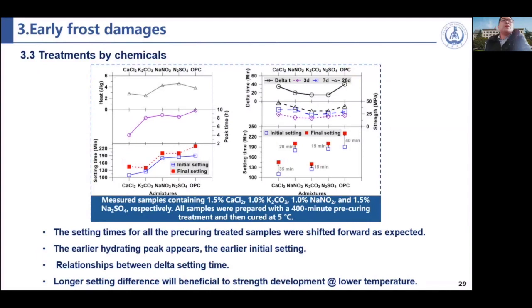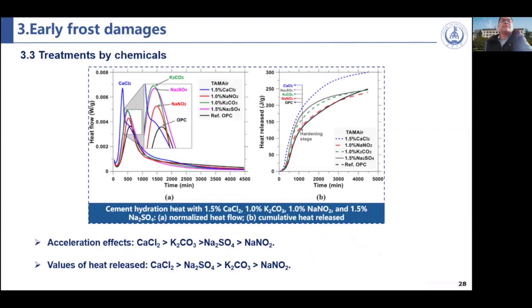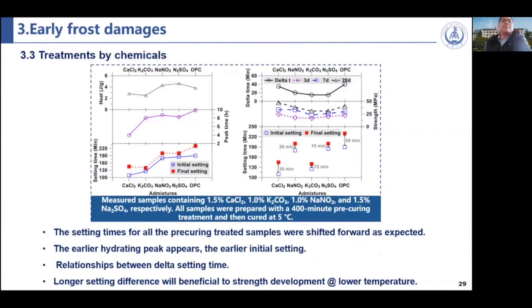And also we want to know what happened during the cement hydration, and how the chemicals influence or affect the cement paste, especially the strength development. We can see this curve is the initial setting and the final setting time, and this is the peak time during the cement hydration. This figure shows the cumulative heat during the cement hydration. So we can see that the peak time and the initial time, the curve and the trend are similar.